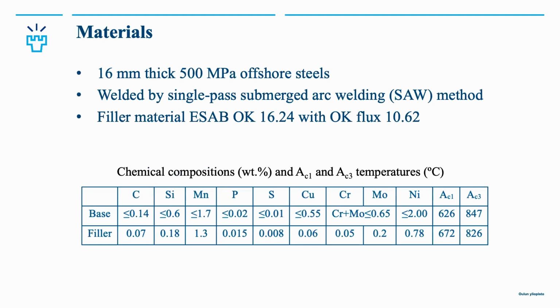Shortly about the materials: they were 16 millimeter thick 500 megapascal offshore steels. They were welded by the single pass submerged arc welding method, which is generally used with this type of steels. And the filler material was ESAB's filler material. And here you can see the chemical composition of both base material and filler material, and also the AC1 and AC3 temperatures calculated by JMatPro based on these chemical compositions.